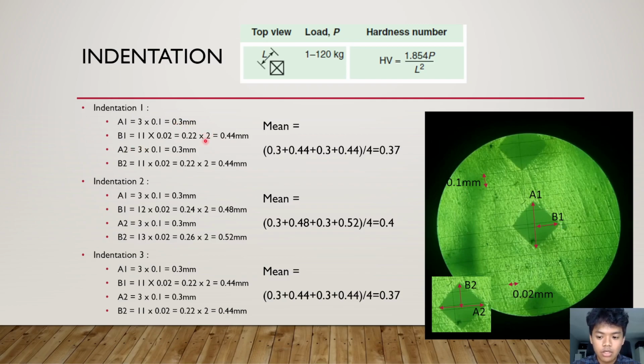Do the same with A2. A2 is the same. However, instead of doing it vertically, you do it horizontally. So A2 horizontally is also 0.3 millimeters, and B2 vertically is also 0.44. So the mean, the average of our diagonal is 0.37 millimeters.